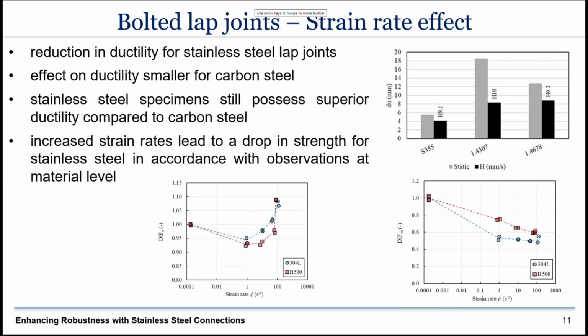So we saw that there is a reduction in ductility for stainless steel lap joints as for carbon steel lap joints. The effect on reducing ductility of the strain rates is smaller for carbon steel than for stainless steel. Stainless steel specimens, even at high strain rates, still possess superior ductility than carbon steel specimens under quasi-static loading conditions. And the increased strain rates lead to a drop in strength for stainless steel in accordance with the observations at the material level. So we were testing more or less in this area.